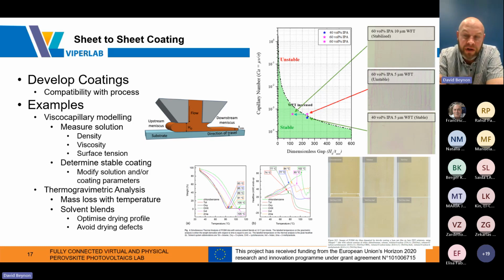Another example of where we use our characterization equipment and analysis equipment to improve our coatings is thermogravimetric analysis. Essentially, this is measuring mass loss with temperature, but one of the areas where we've used it is to optimize solvent blends for the drying profile. So in this case, we were moving from a chlorobenzene solvent, which we could use in our fume hoods, but we wouldn't want to use it for a scaled up process. So by testing different solvent blends, we could match the drying profile which we got with chlorobenzene, which gave a very good uniform coating of PCBM. And by matching the drying profile, we were able to get an equally as good uniform coating by avoiding drying defects.